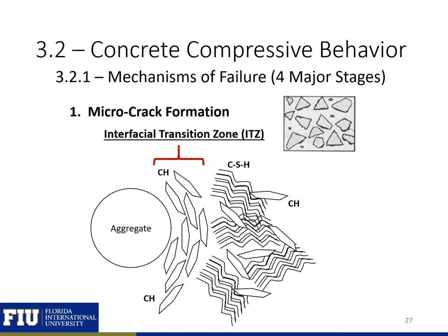The area around the aggregate is called the interfacial transition zone, or ITZ, and is highlighted in this slide. The ITZ is typically the weak point in the concrete matrix. While both CSH and CH form in the bulk hydrated cement paste, CH alone tends to form and orient around the aggregate in the ITZ. This concentration of CH around the aggregate causes a weak point that leads to microcracking and increased permeability.